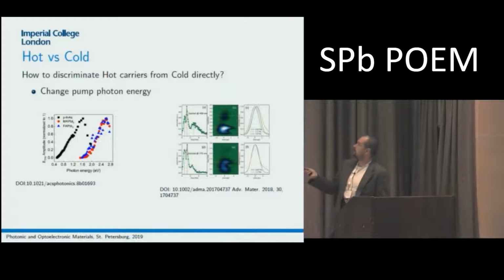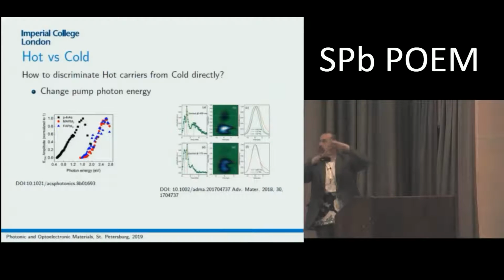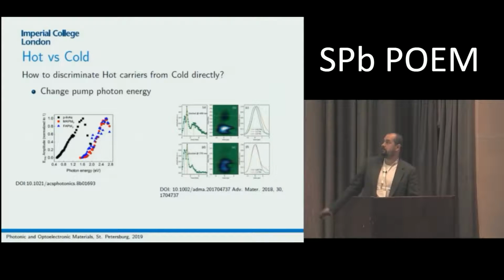And for the dynamics at all the frequencies, they do a short window Fourier transform, where they apply a really short Fourier window across the time domain signal, and they can see that the photocurrent at different frequencies happens at similar times. But when they pump with excess energy at 400 nanometers, a strong peak appears at around 2.8 to 3 terahertz, and the short window Fourier transform reveals different dynamics of the current buildup: at lower frequencies it builds up faster, while the higher frequencies just follow it, which shows the interaction of hot carriers with the lattice, and this frequency is actually associated with this interaction.